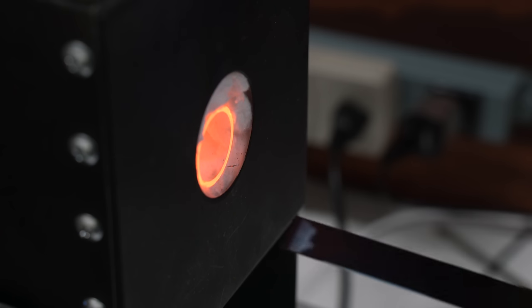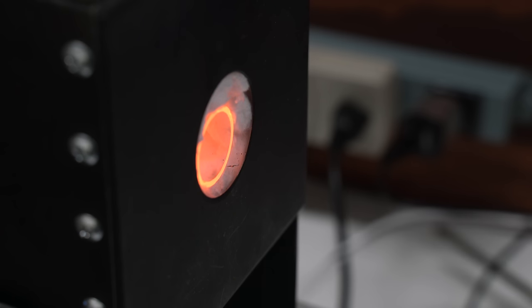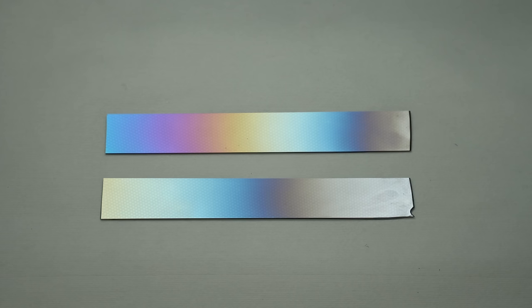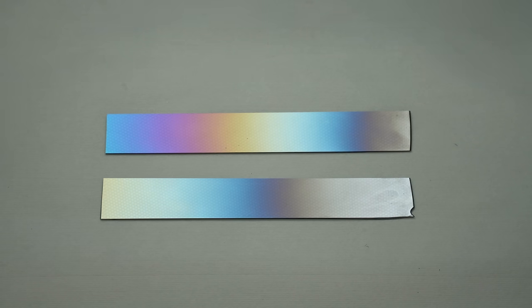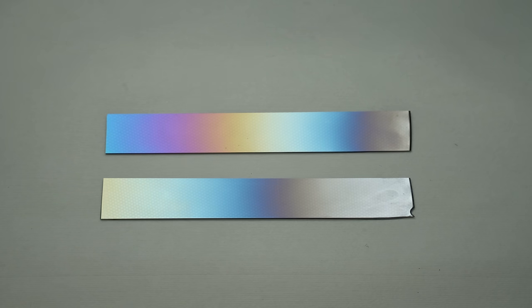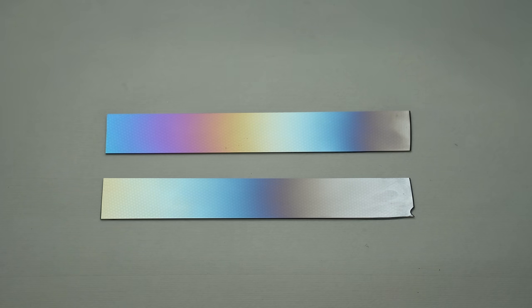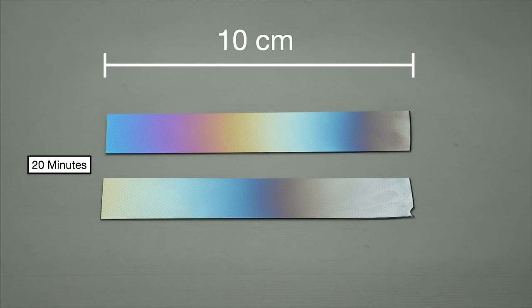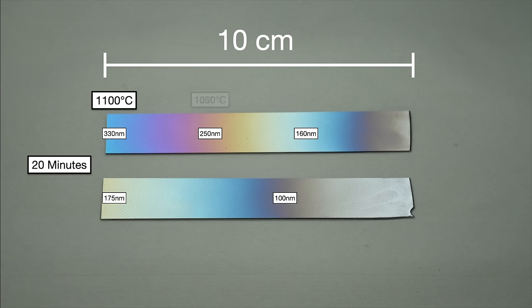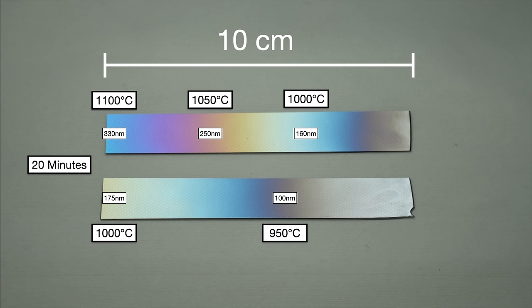I ran this test for 20 minutes at both 1000 degrees and 1100 degrees celsius. This is the result. You can see how the color changes pretty quickly as the temperature falls off. You can use these results to calculate the temperature gradient of your furnace. I start by using the chart to determine the thickness of the oxide at several points. Then I use the calculator to determine what the temperature was at the corresponding locations. It looks like the drop-off is about 10 to 15 degrees celsius per centimeter.